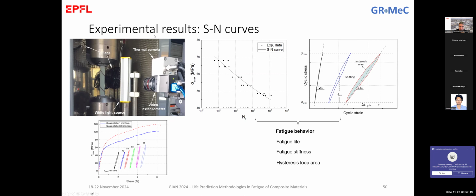So the result of the continuous loading is a typical S-N curve. You see again, if we start discussing the scatter, it is typical of composites. It's a bit higher at high stress levels and a bit lower at low stress levels. And this is also okay in terms of explanation, because at the high stress levels the material is failing due to what we've seen also in the literature, the weak element.